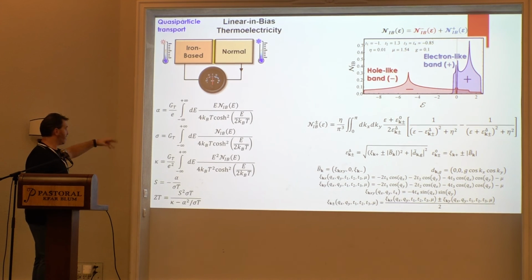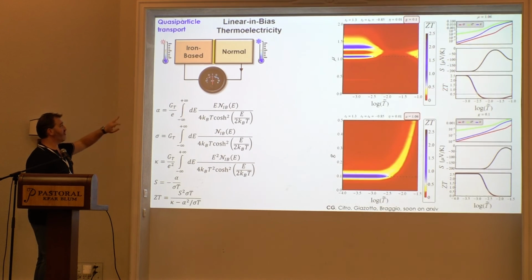These coefficients, the conductances, give us information that is useful for the experimentalist. And we obtained, in the first case, spanning the various parameters, a ZT, which is often used by experimentalists, quite high, a value larger than 1 is good.